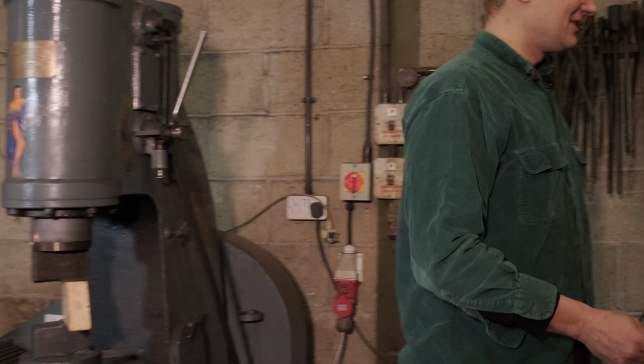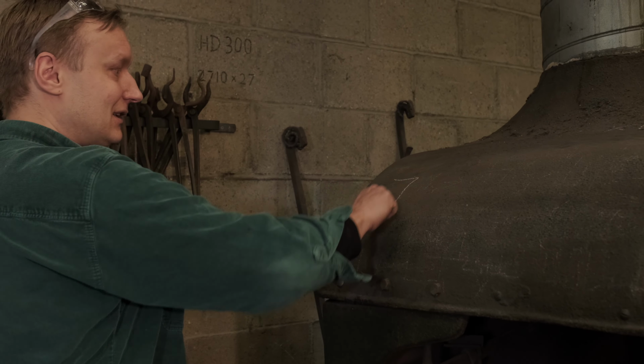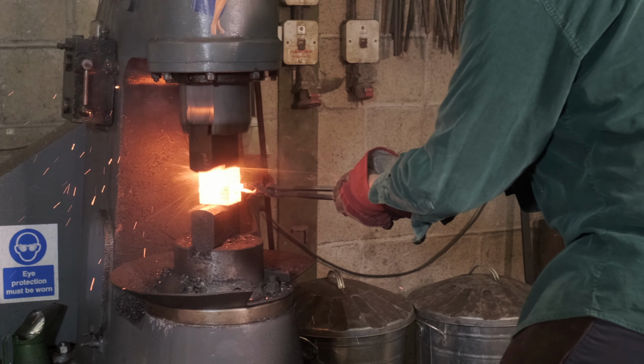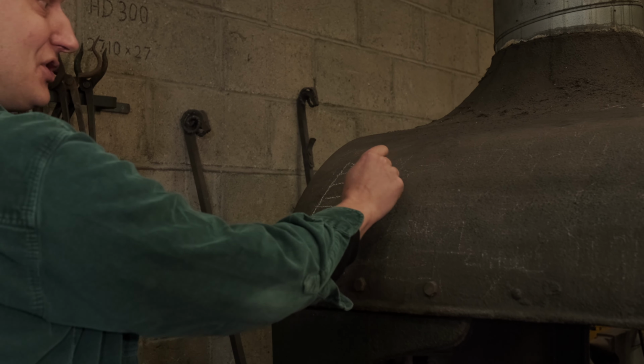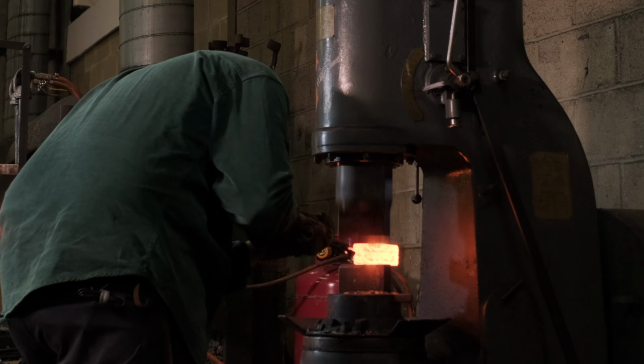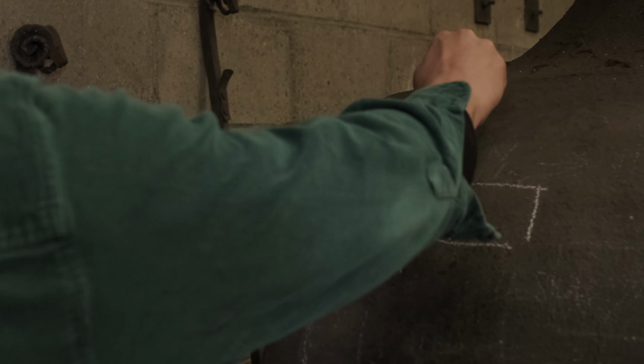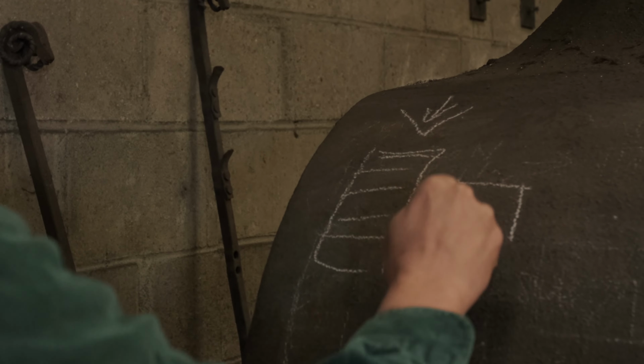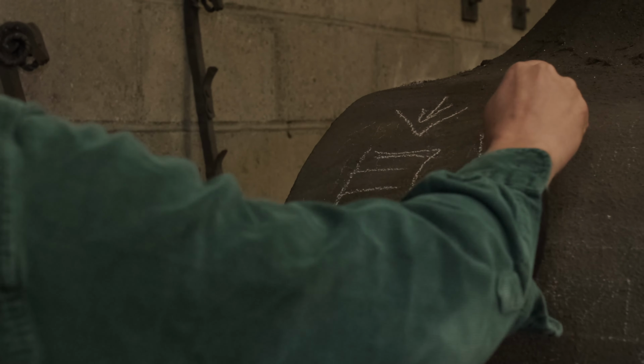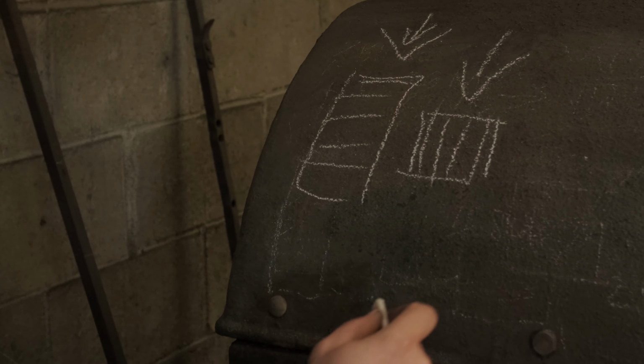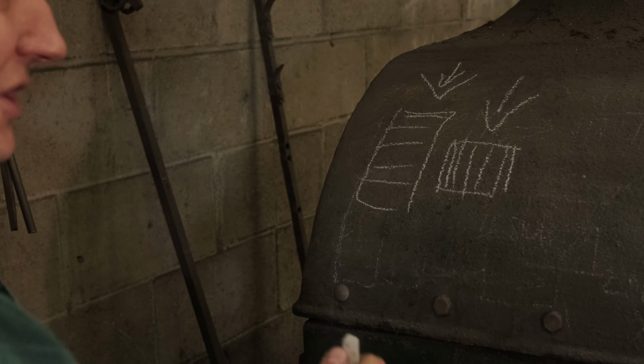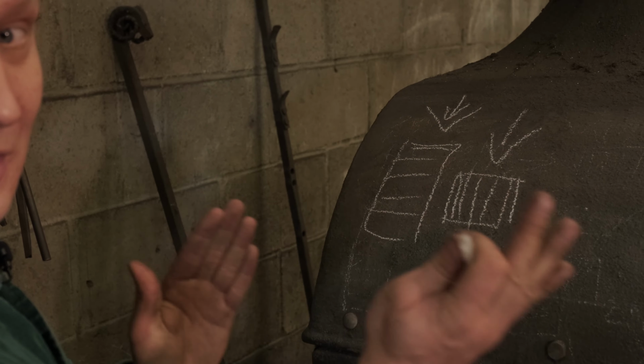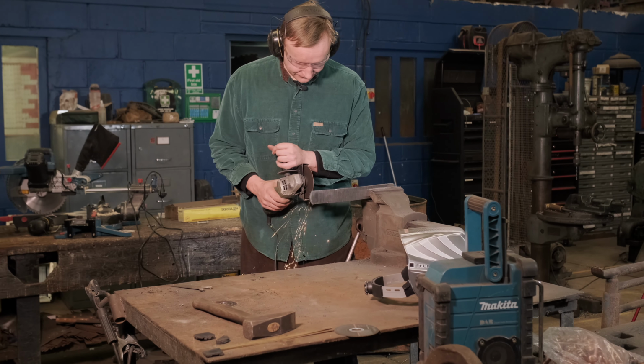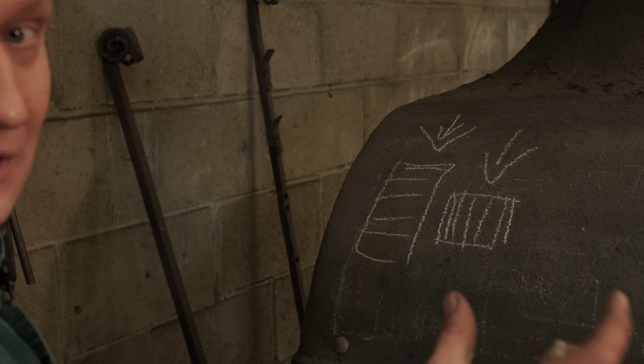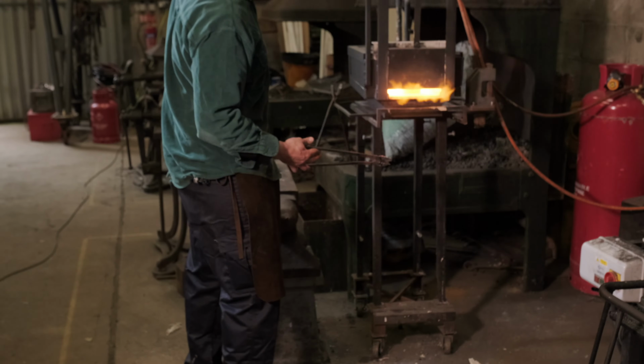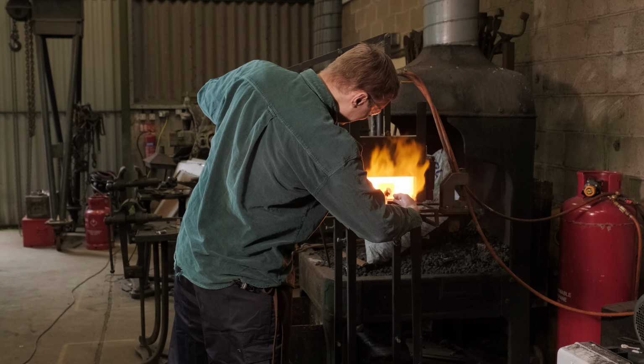So what we're gonna do first, we're gonna forge weld that stack that we've got nice and tight, and then we're gonna actually start forging it sideways. So instead of getting the layers down, we're gonna go with the layers, and we're gonna start forging it this way. That will disturb the layers and actually start forming our pattern. I'm gonna do a bit of an offcut later on, and I'll show you how the pattern looks after the first heat.